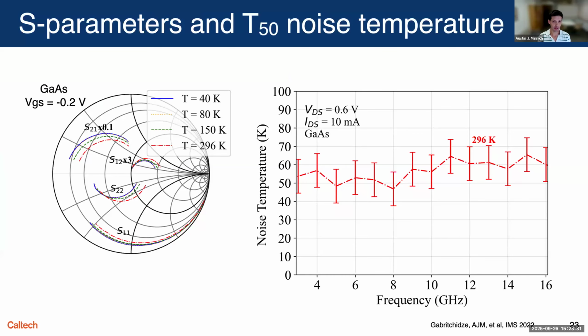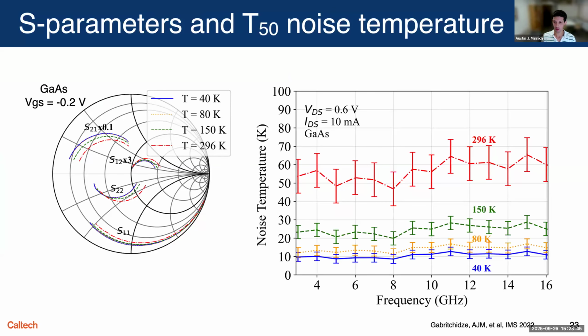All right, so here's the data you can get out of this. On the left are the S parameters, again, on a Smith chart. On the right are the measured microwave noise temperatures versus frequency. This is at the bias indicated in the upper left of the figure. And these are the noise measurements that you get versus physical temperature. And you can see going from room temperature to 40 Kelvin, that's about a factor of 5 or so, which is why every radio telescope has a cryocooler on it. And you can also notice that there's the increment by which the noise improves for a given temperature change. It's not uniform completely. In particular, between room temperature and 150 Kelvin, there's a particularly big improvement. And we'll look at that as a kind of a clue later.